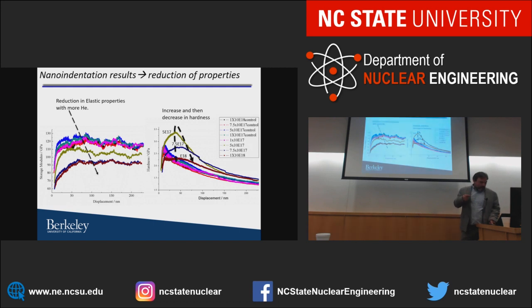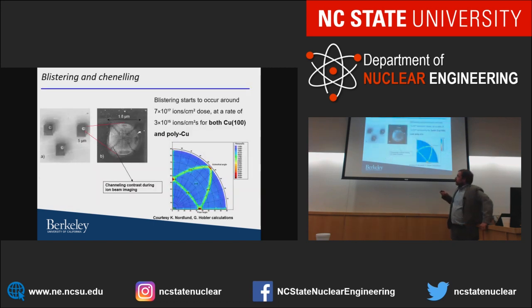And I pointed out earlier that at 10 to the 18 or so, we see these blisters here on the surface. We see these X formations. And we see, actually, if you look carefully here, also sort of a cross in between. Now, those look very much like slip steps. And since this is copper, and the shear planes are 1, 1, 1, so this is on the 1, 1, 1 planes, we see the formation of these blisters developing.